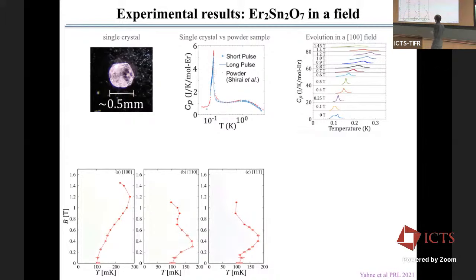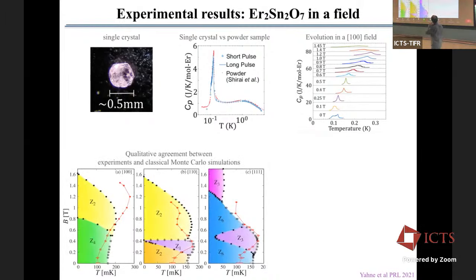And when we do Monte Carlo simulations of that, we can see, so we don't have a quantitative fit, but qualitatively, we have the same phenomenon. Monte Carlo shows one reentrance here, two reentrance here, and one and the beginning of a second one here. So which means that classical Monte Carlo can reproduce the reentrance phenomena in erbium stannate, not quantitatively, but we can reproduce the physics, which means we can use Monte Carlo simulations to try to understand the mechanism behind reentrance here.